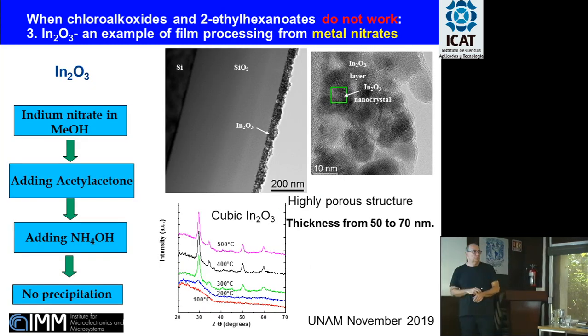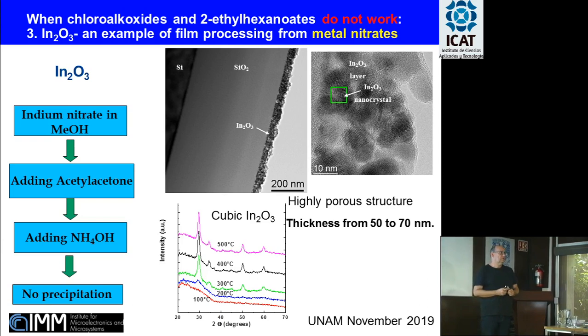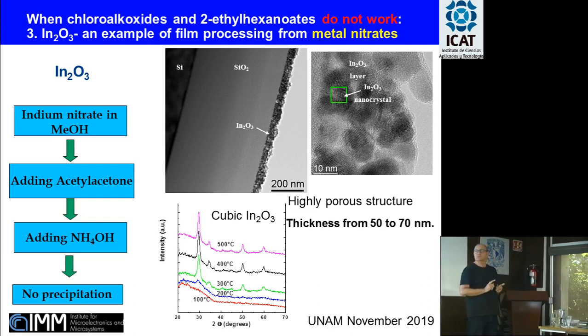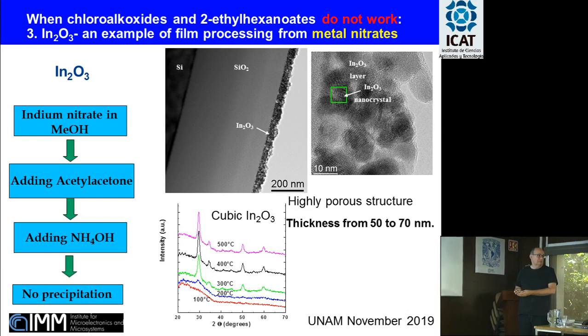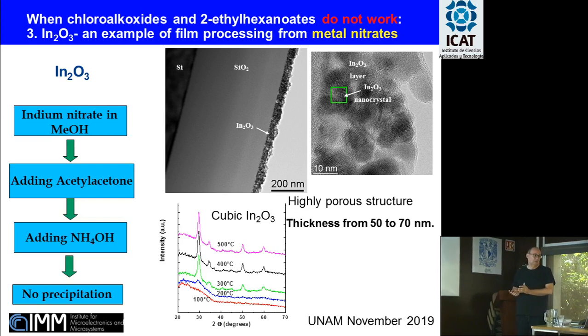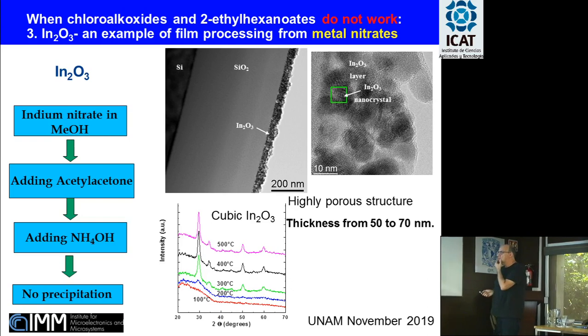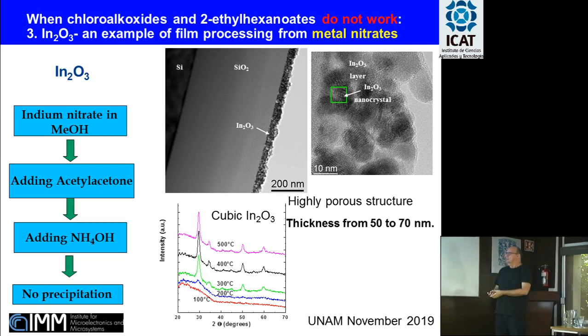But there is one more case when we cannot use chloroalkoxides, we cannot use ethyl hexanoate, like, for instance, another important oxide like indium oxide. Why? You can buy the alkoxide, but it is really expensive. You cannot use it easily because it is very reactive. The ethyl hexanoate, same problem, it is very expensive. So the chloroalkoxide cannot be prepared. So how to solve it in this case? Well, we use a simple indium nitrate, a simple inorganic precursor.